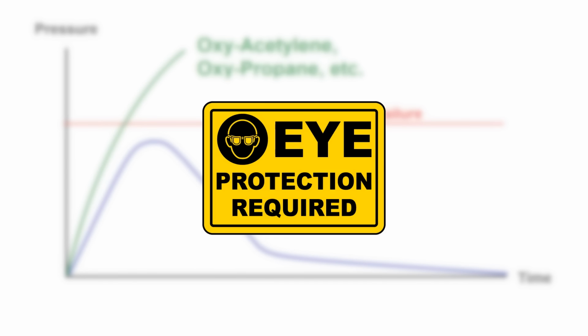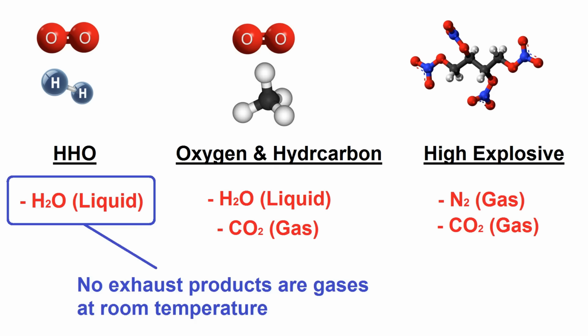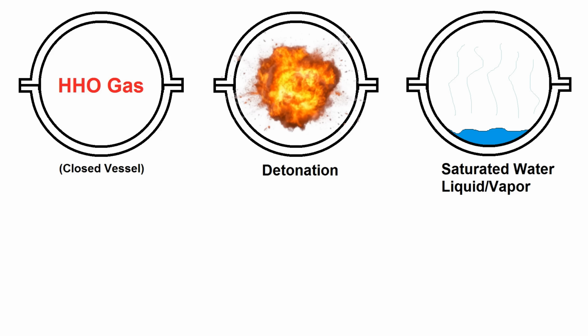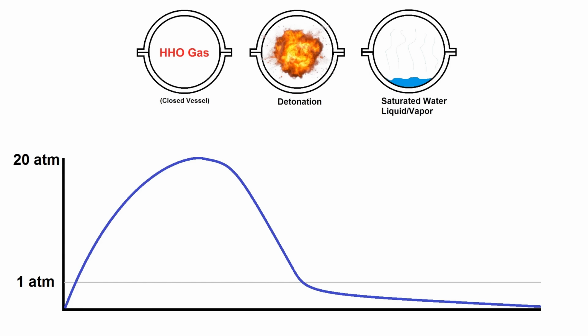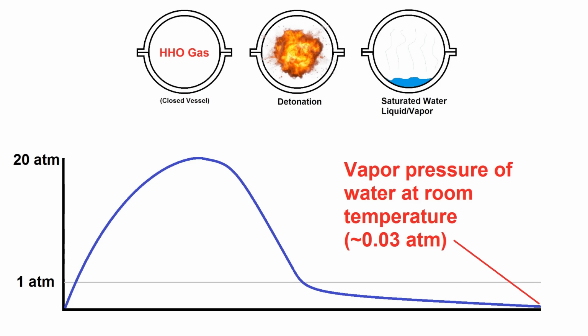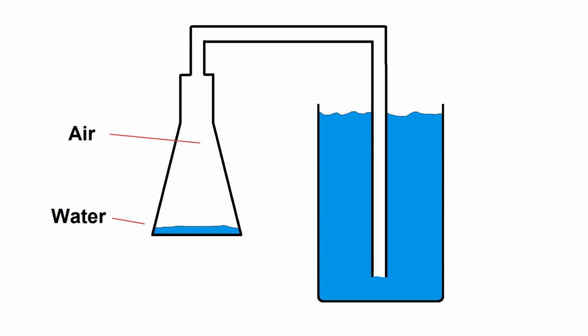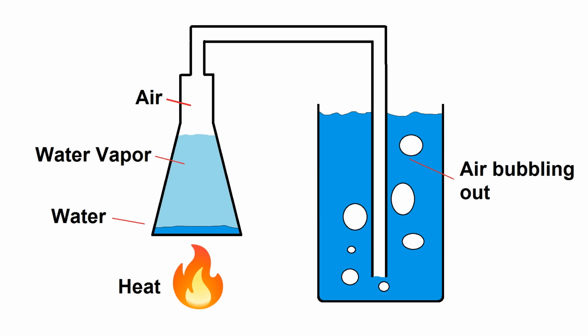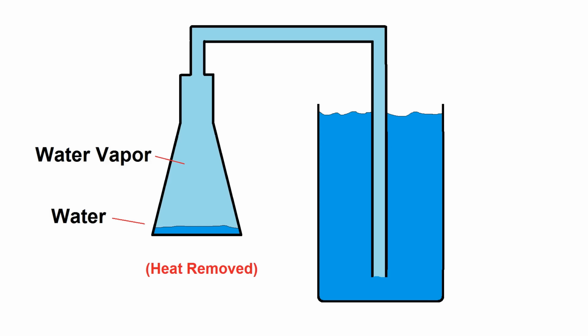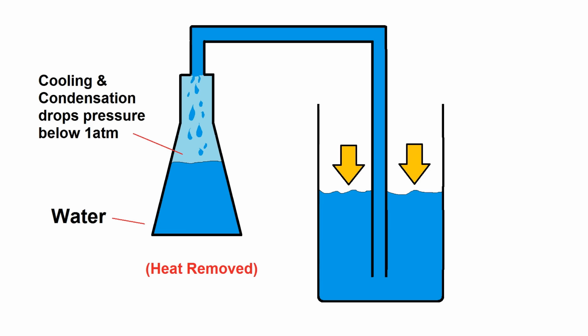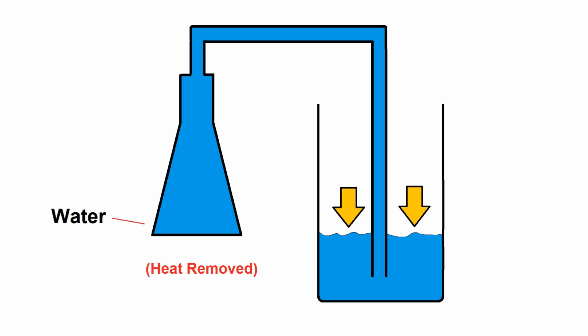In addition to that, the combustion products of HHO detonation aren't gas at room temperature since the product is just water. So if you had a closed container at 1 atmosphere full of HHO that you ignited, you'd get an overpressure of around 20 atmospheres peak. But once the resulting vapor cooled and condensed, you'd actually end up well below atmospheric pressure. This is the same effect you can see with so-called steam vacuum, where all the air in a container gets displaced by water vapor, but when that vapor cools and condenses to room temperature, the vapor pressure is below 1 atmosphere, so it causes a suction.